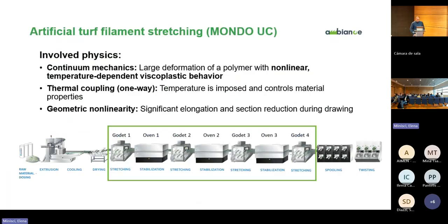So what we have done here is to try to focus on this stretching process. We have several physics involved behind it. Basically, in this case, we are dealing with the large deformation of polymer melts and solids in this transition. This is in the field of continuum mechanics from the simulation point of view, where we have a strong dependence of properties on temperature. That is something we need to take into account. And we also have what we call geometric nonlinearity. That means we have a lot of deformation to be modeled, which the material undergoes from the beginning of the stretching stations to the end.